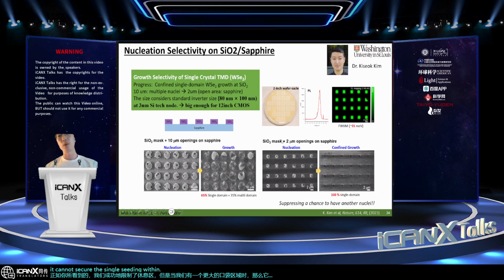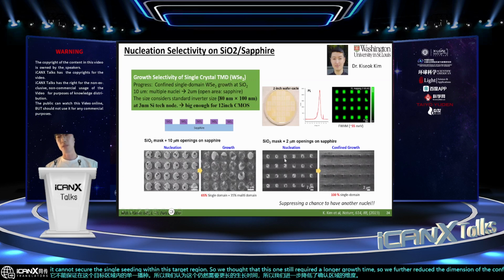But when we further reduce it, we thought that this one still requires a longer growth time. So we further reduced the dimension of the confined region, so that eventually we can secure a single seed inside this target region, and eventually you can produce a single crystal material at a large scale.